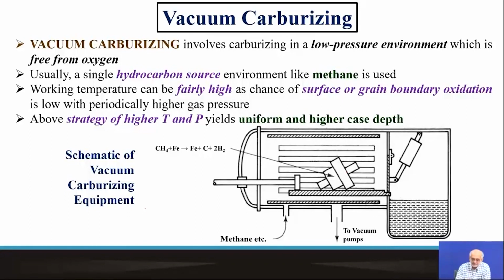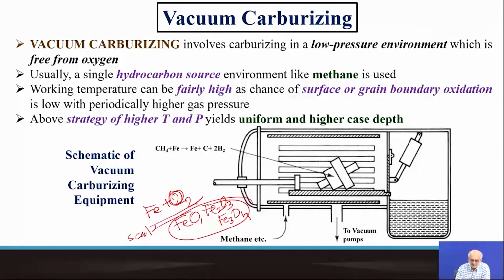So because it is likely to form one of these oxides, which essentially contributes to the so-called scale formation. And this is detrimental. We don't want this, because once you have a scale formed onto the surface of steel, then diffusion of carbon becomes practically impossible, because now you have an impervious, so-called barrier layer of oxide, and this oxide doesn't allow carbon diffusion inside.